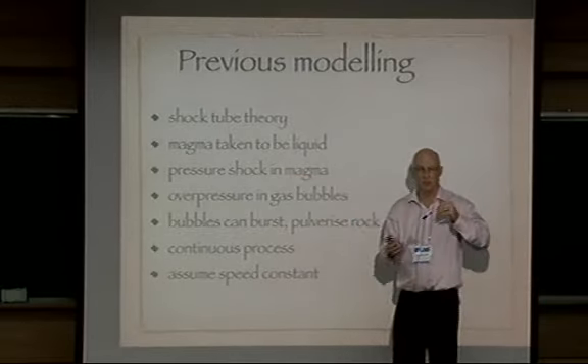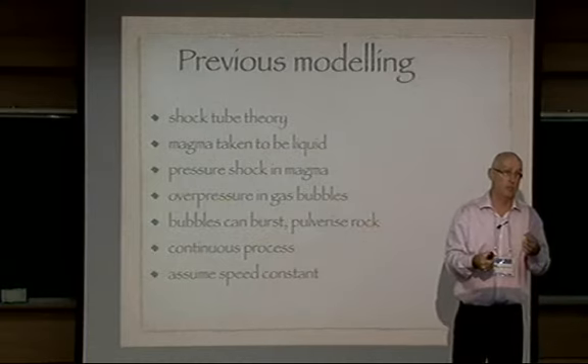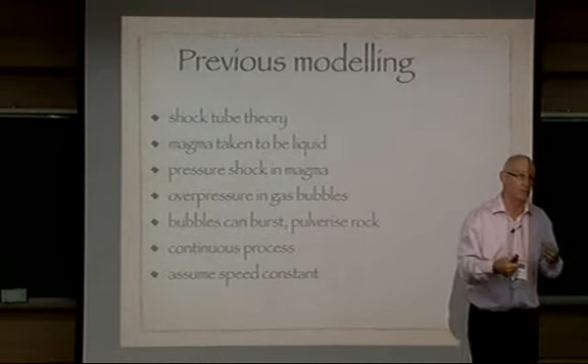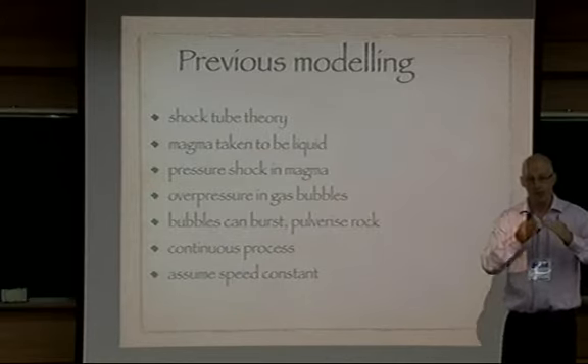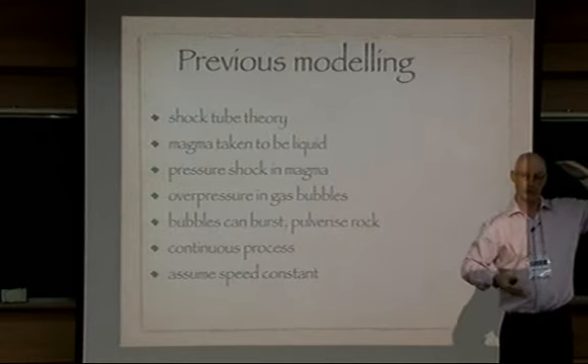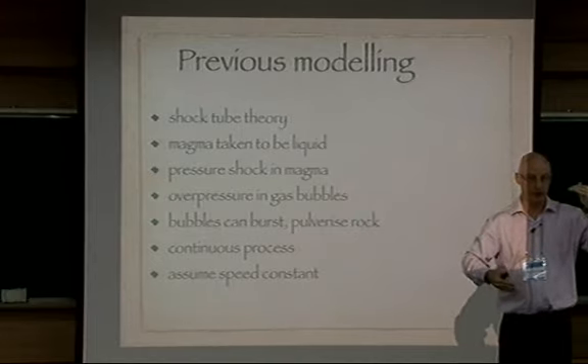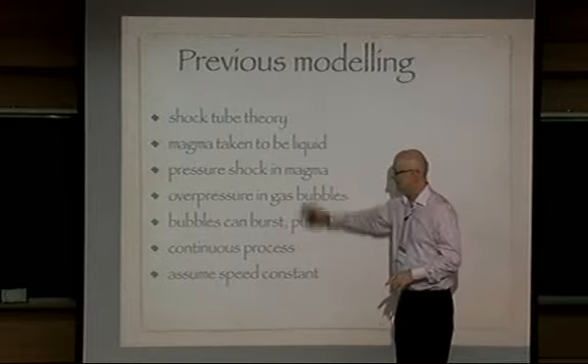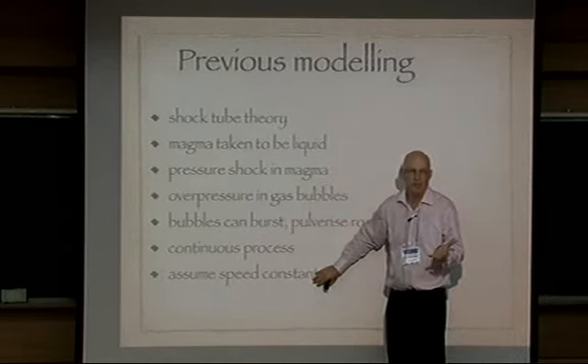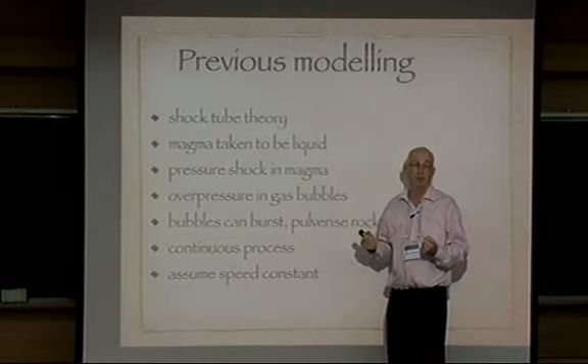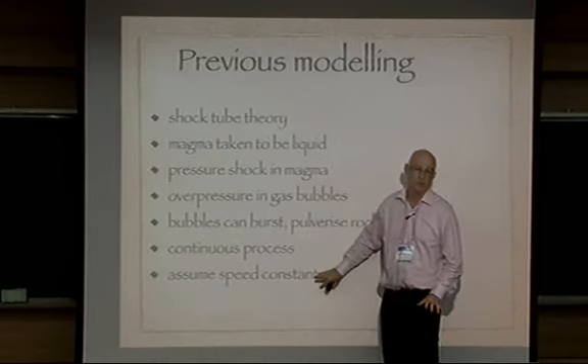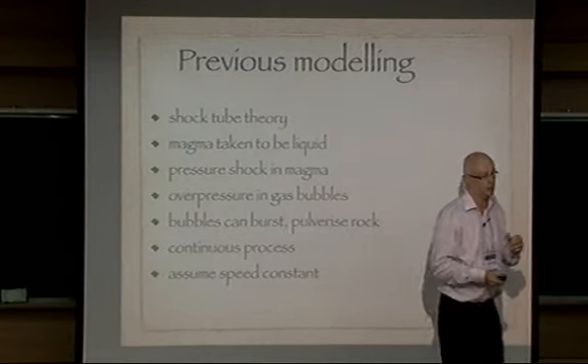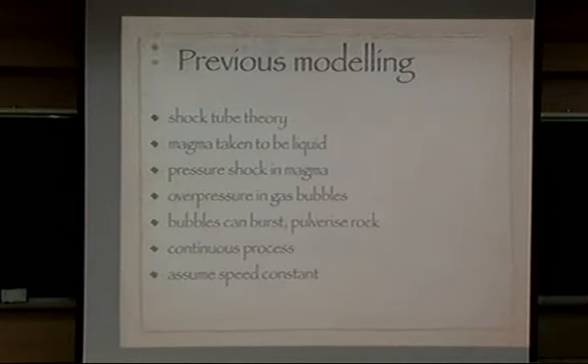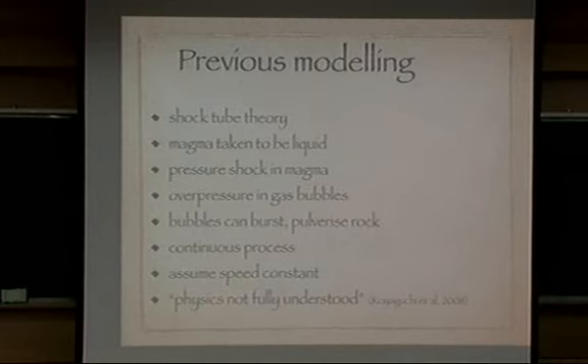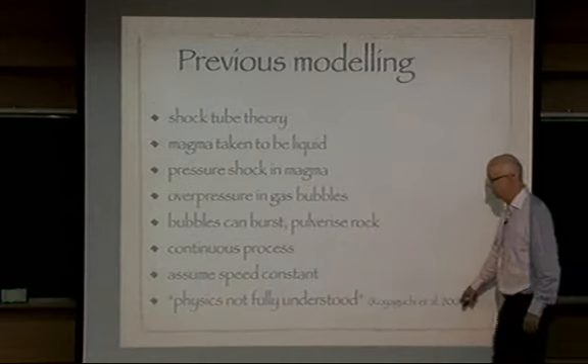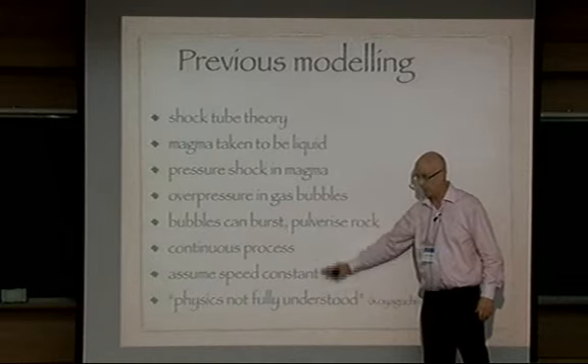Across this pressure drop, they solve the conservation of mass and conservation of momentum, which is good. That's what we do too, mass and momentum conservation. But it's done in an average sense, just across a jump. Then to progress the calculations, you need to assume something about the speed. What's the speed of the fragmentation? It doesn't come from the modelling, so let's assume a constant speed. The volcanologists have got some results, and Koyaguchi et al. in 2008 admitted that the physics is not fully understood from the modelling that's been done before.